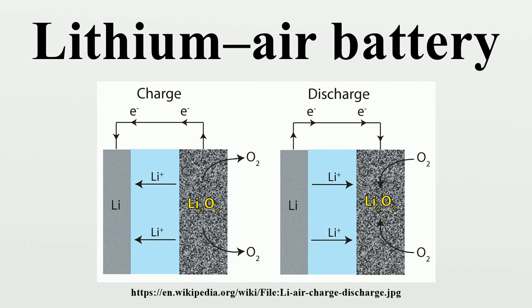In a cell with an aprotic electrolyte, lithium oxides are produced through reduction at the cathode. Li+ + e-, O2 + * -> LiO2*, Li+ + e-, LiO2* -> Li2O2*. The asterisk denotes a surface site on Li2O2 where growth proceeds, which is essentially a neutral Li vacancy in the Li2O2 surface. Lithium oxides are insoluble in aprotic electrolytes, which leads to cathode clogging.